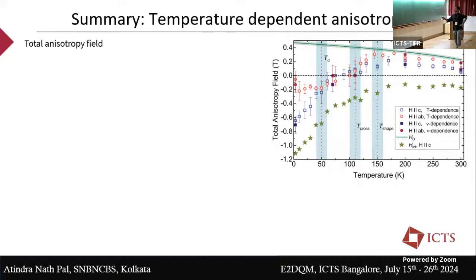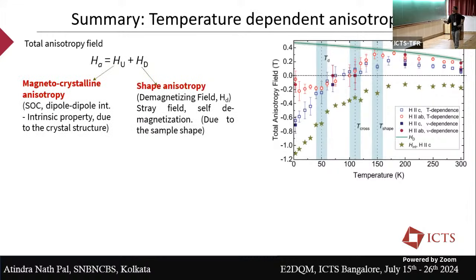Okay, what you observe, so this is the H parallel to C, red data is H parallel to AB, and these blue data points are the H parallel to C, and you can see there is a deviation. This is more or less agreeing, but at low temperature it actually deviates below, and this temperature is close to 50 Kelvin. Okay, now one can actually assume that total anisotropy field, you have 2 components, right?